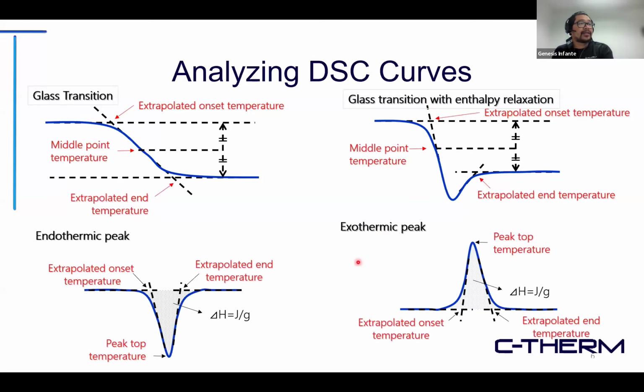And of course, for the endothermic and exothermic peaks, again, onset temperature is something along the line of a tangent line, where the peak temperature or the middle point intersects with a baseline. So that's how we define onset temperature. So again, if you're looking for something like a melting temperature, this is where we would define it, not the peak temperature right here, but the onset temperature. And the end temperature, again, is a useful temperature to take note of, just in case you have more amorphous semi-crystalline polymers, as we would be discussing later on.